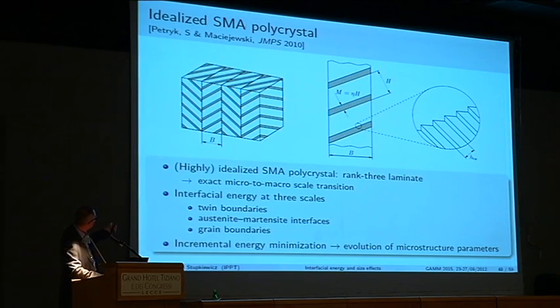But at the end, if we assume that each of these grains transforms through formation of a laminate, then considering also lower laminates in the martensitic plates, the twinned laminates, what we get is a rank 3 laminate. After making this high idealization, this assumption of this kind of microstructure, further on we can apply our micromechanical tools, and for laminates we have exact micro to macro scale transitions. That's why we use this, of course. So after adopting this assumption, the rest is really strict, the analysis is strict.